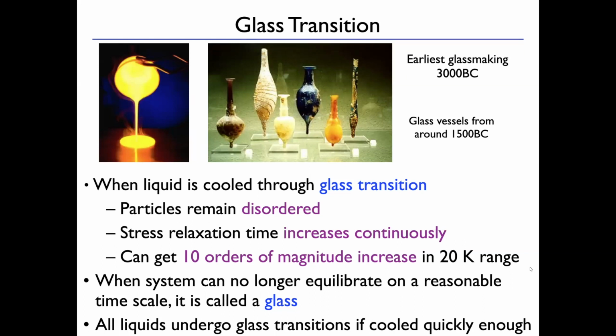So what is the glass transition? The idea is you take a liquid, right? You cool it through the glass transition. And if you cool it extremely slowly, what happens is that it'll tend to crystallize. But if you cool it fast enough so that you can't form nuclei of the crystals, the crystal nuclei, then you don't crystallize. And as you keep cooling it, what you find is that it remains a liquid. The particles remain in a disordered structure. But the time that it takes to equilibrate the system, to reach thermal equilibrium, which we call the stress relaxation time, or simply the relaxation time, increases continuously.